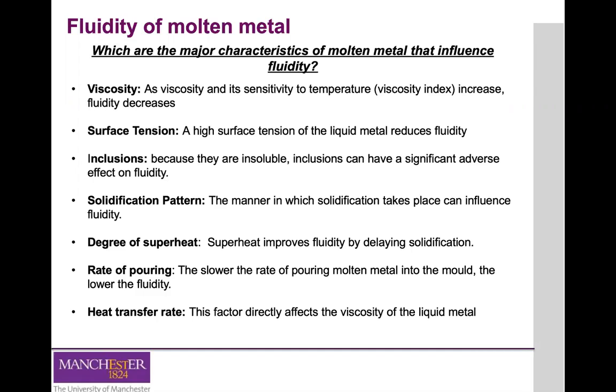Viscosity is one of those things that can affect the fluidity and therefore the filling of the mold. As the viscosity increases, and also the sensitivity of the viscosity to the temperature — defined as viscosity index — increases, the fluidity will decrease and therefore it will be more difficult to fill in the mold cavity. Surface tension is also another important characteristic of molten metal.